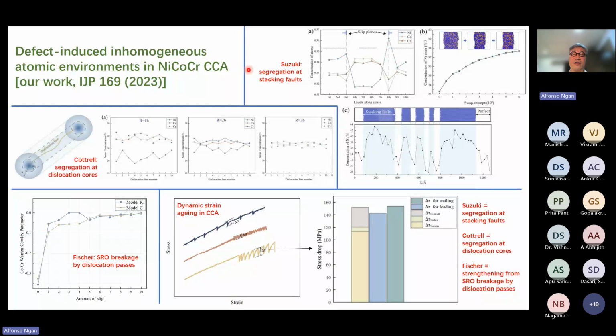The nickel of the three elements here tends to segregate on the stacking faults. So this is one type of segregation that would occur with a dissociated dislocation, with a stacking fault in between. And for either of the two Shockley partials, we may also have the Cottrell segregation as well. So in this case, some elements will segregate to the dislocation core. So this is known as the Cottrell segregation.